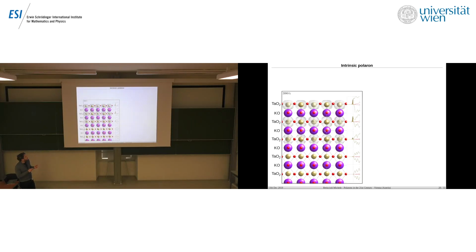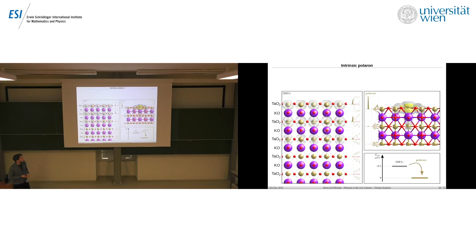And these electrons occupy the bottom of the conduction band with decreasing intensity as soon as you go deeper and deeper into your slab. But actually, what we propose is a different paradigm, a different scheme, which is able to accommodate this charge in a better state, which is the polaron formation.